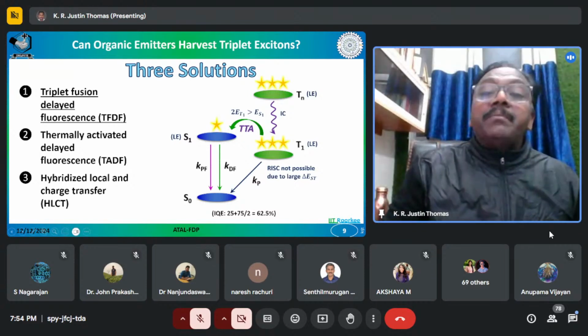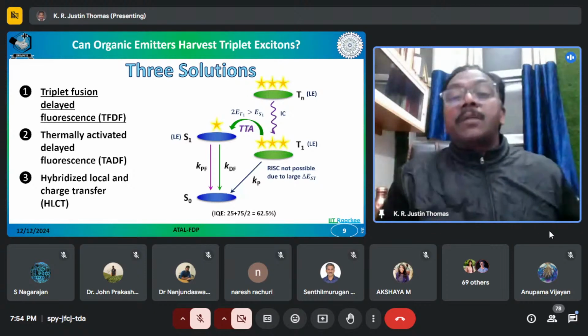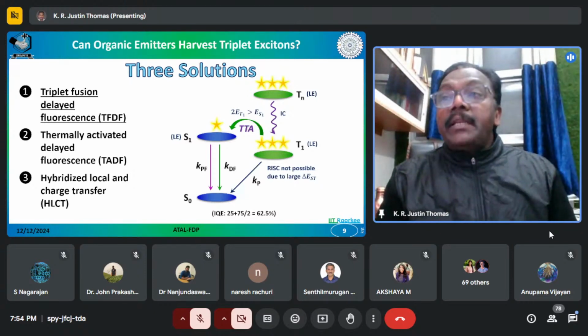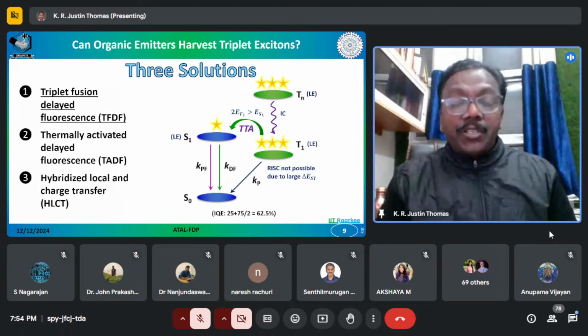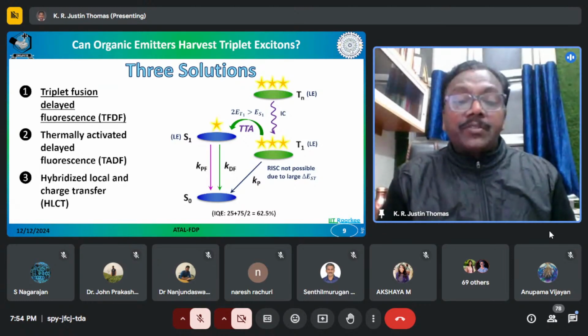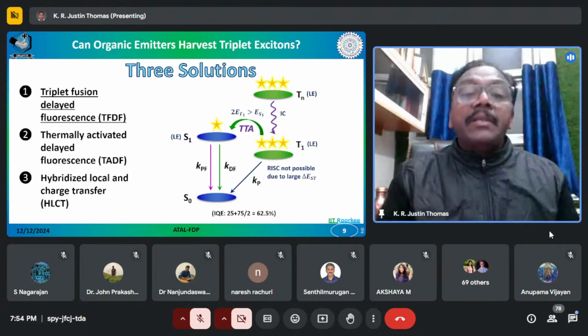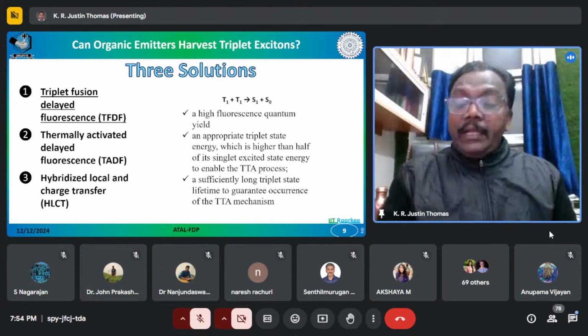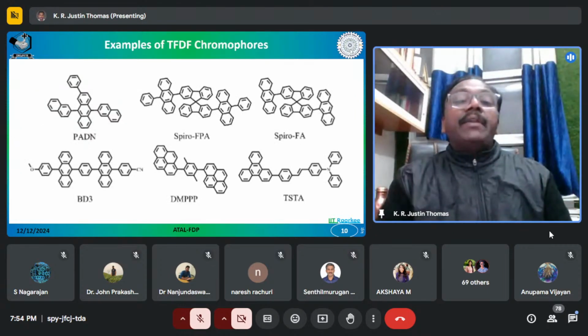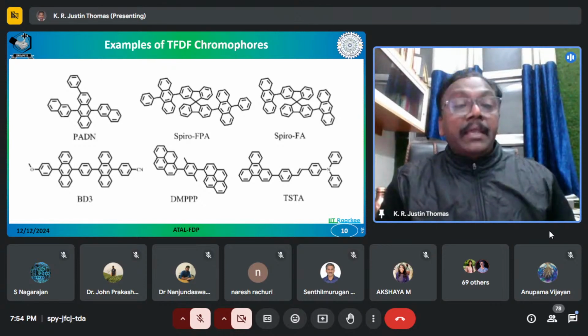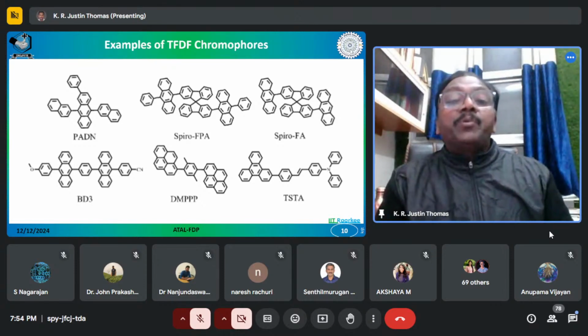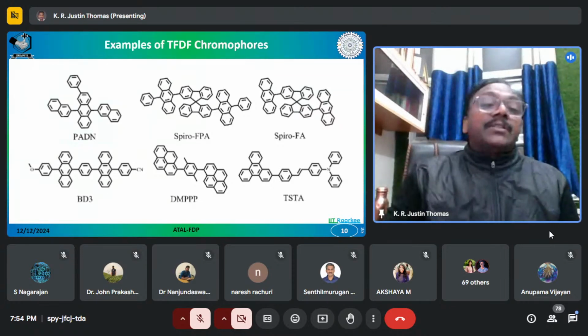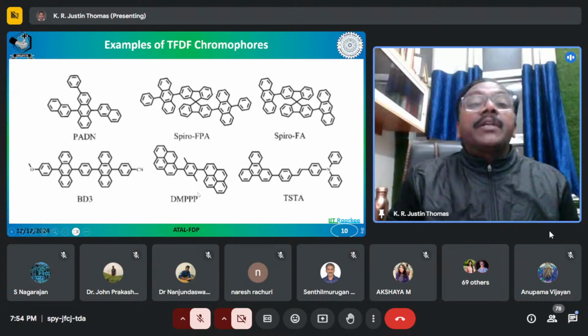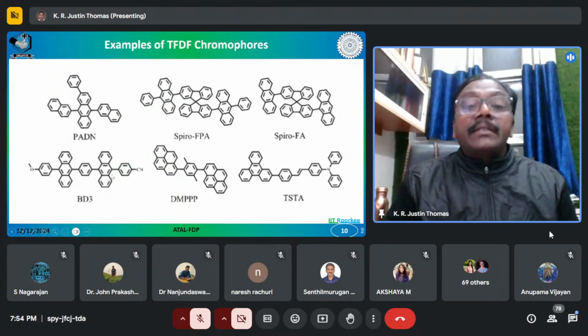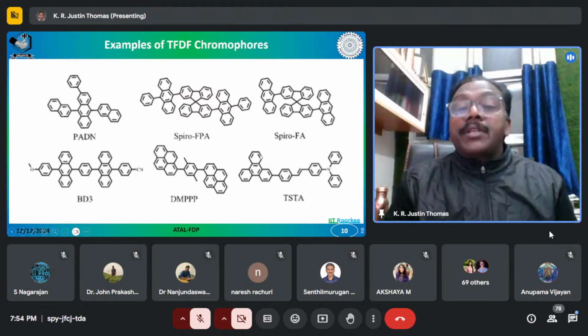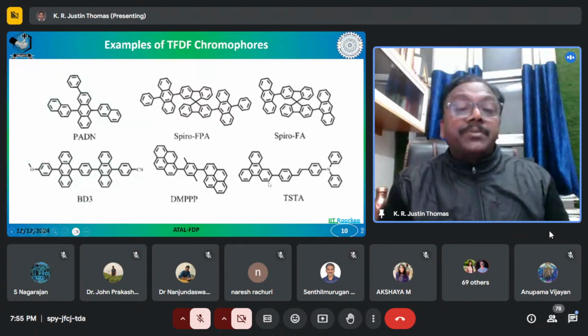But the challenging problem with these molecules is that most of them are polyaromatic compounds. Their solubility in commonly used solvents is very low, so the processability is also low. As you will see with the examples, they all have an elongated conjugation, and because of that, they have very poor solubility in most solvents. So you can see these are examples of compounds which show TFDF. Many of them have anthracene, pyrene, or bifluorene structures, or other polyaromatic systems.